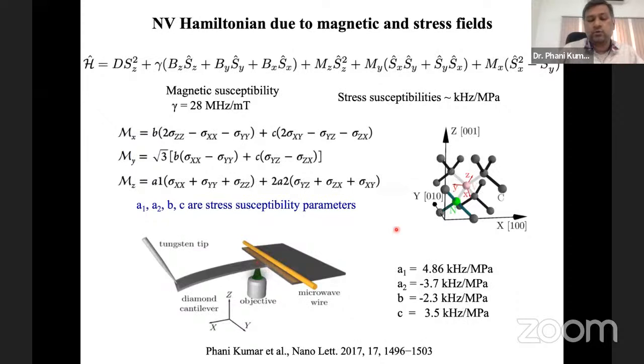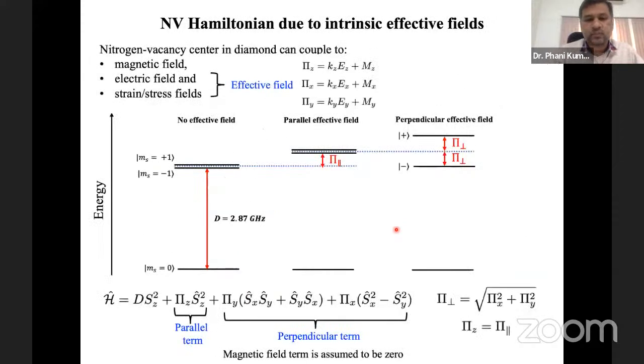During my postdoc we did some detailed studies of the stress susceptibilities, and we measured them to be on the order of a few kilohertz per megapascal. Again, you see the stress fields also only weakly change the response of the NV center.